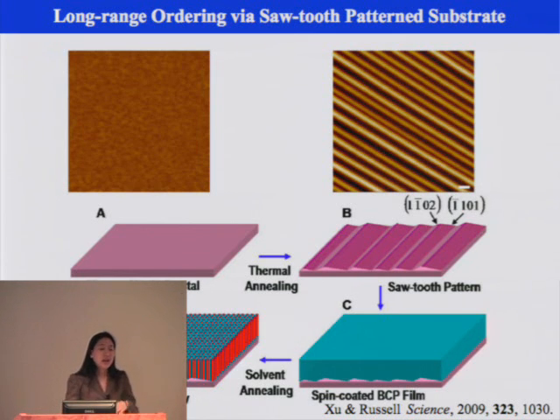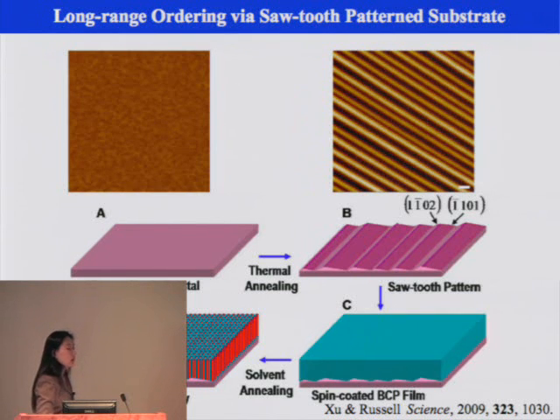If you scan in any area - say an inch by inch square size of the sapphire - you can see that wherever you scan, they are going to be in registry with each other. The whole idea is that subsequently you have your polymer in there. How the polymer is going to order is going to be biased by the underlying substrate. If you select the pitch and periodicity between the trenches properly to match what you see in the polymer, you should be able to direct the polymer assembly over a macroscopic distance.